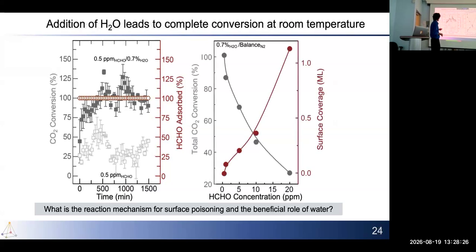What we found very interestingly is that once you start adding water to this reaction, so it's about 0.7% H2O here, you get really close to 100% conversion. So you're able to run this reaction at room temperature with near full conversion if you add relative humidity to this reaction.